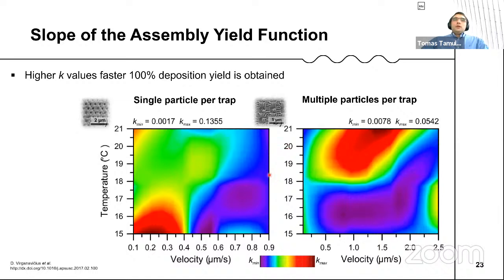So let's say if you are willing to work with a single particle per trap, maybe it's worth to go lower in velocity and lower in temperature. And when you have multiple particles per trap in your designed template, then maybe it's worth to go faster and at higher temperatures. So you have to play around and find the conditions, but when you find them, it's like 100% yield.